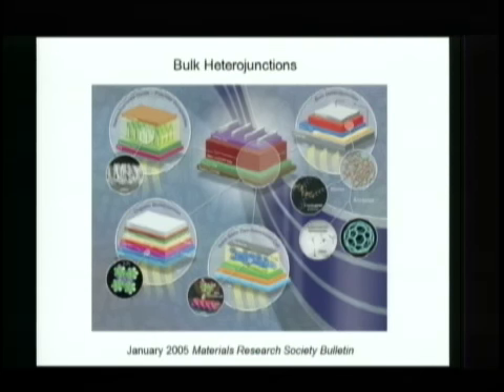And this is from the cover of the Materials Research Society bulletin, and you see different approaches that people were using. They would grow brushes of nanowires and fill them in with a semiconductor, or they would take a donor made of a polymer and an acceptor made of fullerene molecules and cast those films and get a blend, or they would smear down crystals of titania and then coat that with dye molecules. There are lots of different ways to make what we call a bulk heterojunction. And now, no matter where the exciton is formed, it'll be right at the interface between the donor and the acceptor, and so we can separate that.